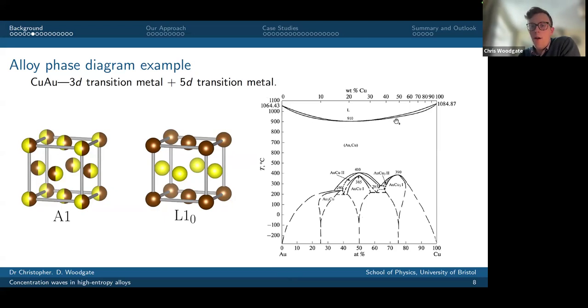This is where the alloy essentially is melting or solidifying, depending on whether you're heating or cooling it. And then there's this big region here that's denoting the solid solution, the situation where the atoms are substituting for one another randomly. And if I look specifically at the 50-50 composition, if I imagine cooling my alloy from the melt into this solid solution phase, eventually there is a transition marked here.